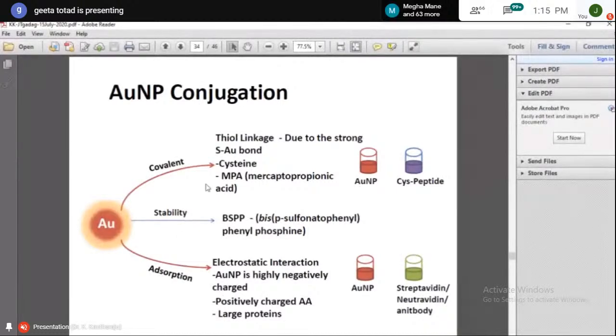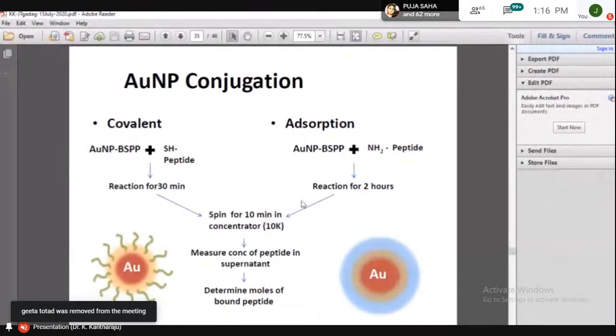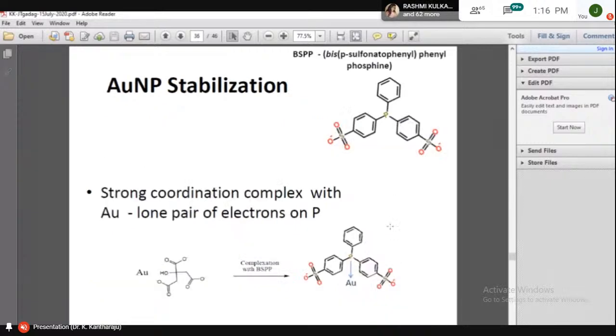Then we went for covalent. We already know that the sulfur and gold bonding is going to be very effective by using BSPP as a stabilizer, because nanoparticles, if you keep them as they are, can't be stable because of their electronic nature and are highly reactive. So we are going to mask that, using a stabilizer, and with the stabilizer we make this sulfur linkage. This method is very simple and is done in a simple flask, not in a round-bottom flask or beaker. This is the stabilizer, and what it does, you can check, is pull out electrons. So obviously, the gold is going to have a more electron-positive nature.